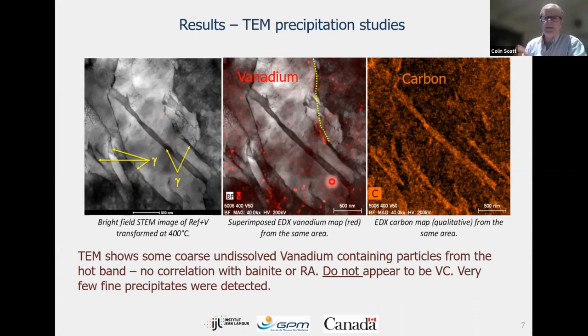This image here is a chemical map. So we're doing an EDX map with vanadium. And so the red color is where you see locally higher concentrations of vanadium. And you can see some segregation of vanadium. It looks like precipitates. But when you look at the associated carbon map, then you see carbon enrichment in the austenite laths, the retained austenite laths, but you don't see these precipitates as being carbides. So we don't think they are.